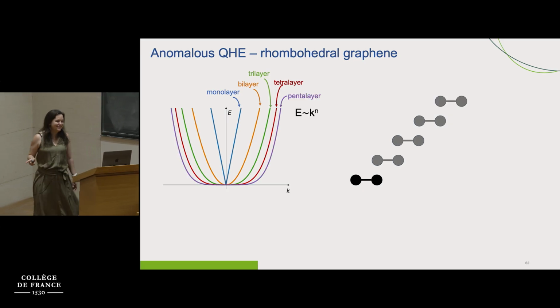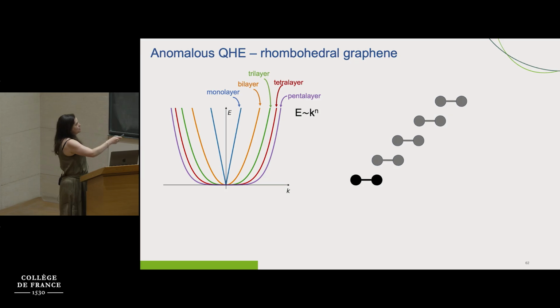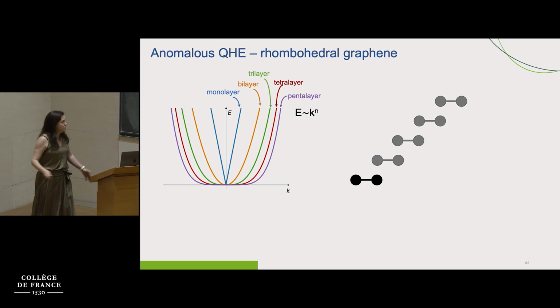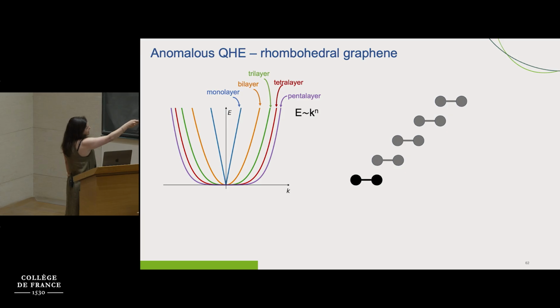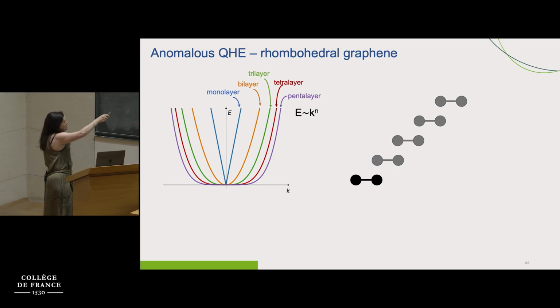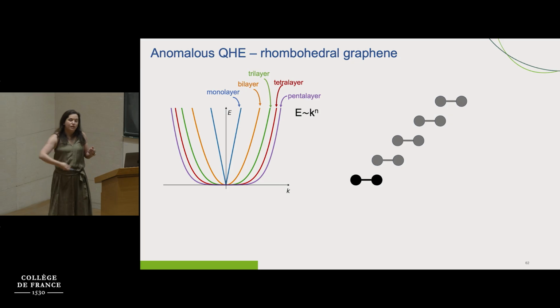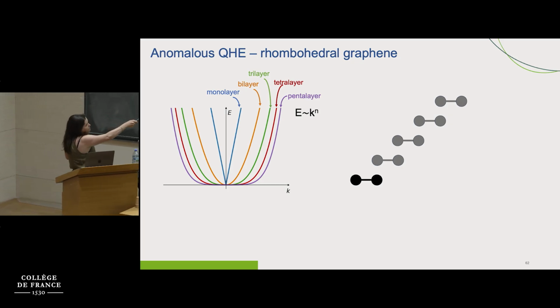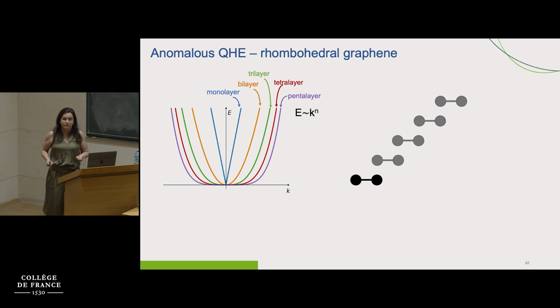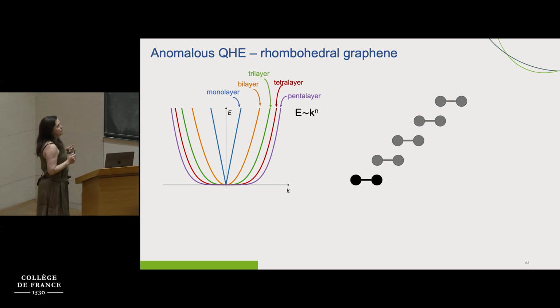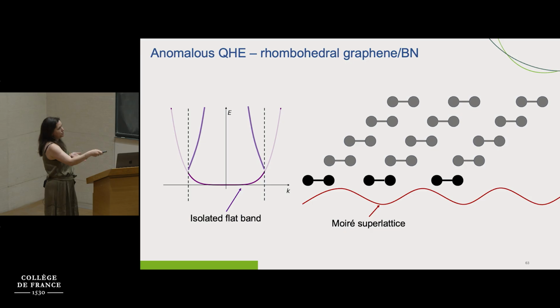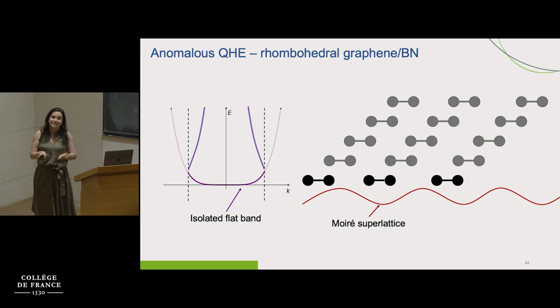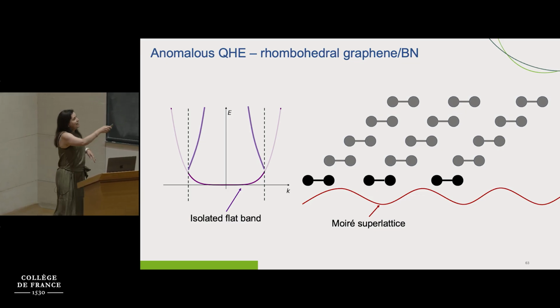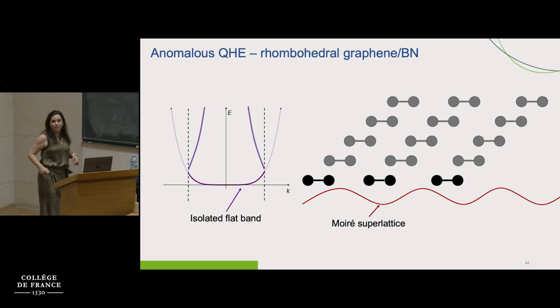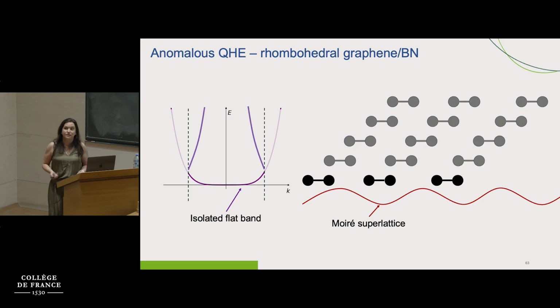What is interesting here is that the energy dispersion goes, as a first approximation, roughly as a power law of the number of layers, which means that every time you add a layer, you're going to have an even flatter band near the charge neutrality point. So now you can imagine, if I add a Moiré potential to all this, then I'm going to make the same thing I did before, this band folding, and I'm going to isolate my flat band. So is this possible or not?